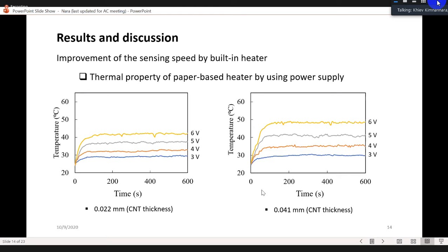And not different from the previous one, at 0.041 millimeter of CNT thickness, the temperature is around 29 degrees Celsius when we apply 3 volts, and then it can further increase to around 35 degrees Celsius when we apply 4 volts. Then it can be increased more to around 40 when we apply 5 volts, and it can reach around 48 degrees Celsius when we apply 6 volts.